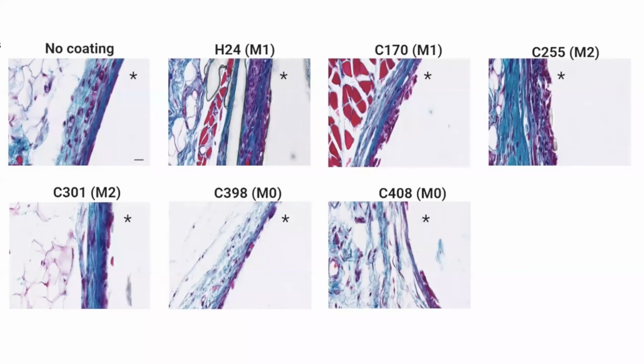And based on this, what we hypothesized was that maintaining the macrophage phenotype at a naive state actually could contribute to better resolution of inflammation. And actually that is in line with what we know about homeostasis, where naive macrophages actually contribute and maintain homeostasis. But the bottom line is that with these different polymers, we can differentially induce a state of polarization that reflects in the tissue response, collagen deposition, cell infiltration, and fibrotic capsule formation.